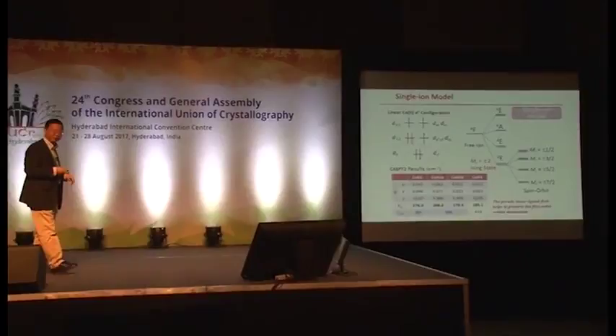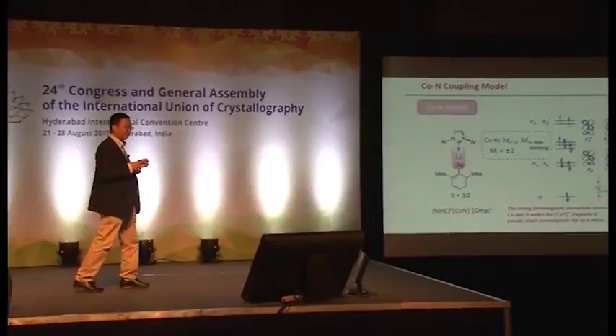We can use a single ion model to make some calculation, and it shows the perfectly linear ligand field helps to preserve the first order orbital moment. So it has a strong uniaxial anisotropy. But for the third compound, the energy barrier based on this calculation has a slightly bigger difference. Another model we use is the cobalt nitrogen coupling model. In this model, due to the strong interaction between the cobalt and nitrogen, it's not ferro, it should be antiferro.